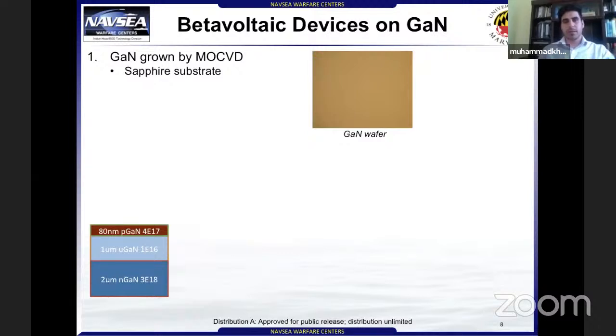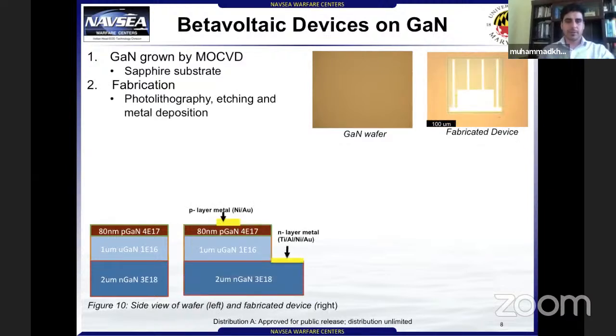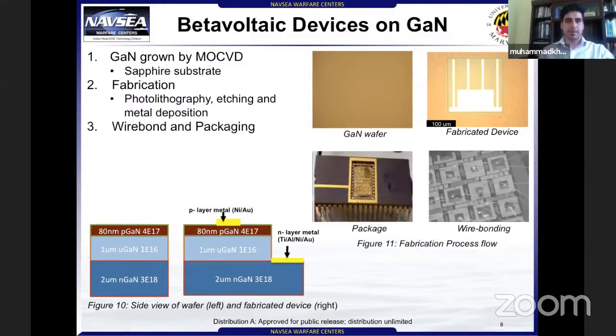We fabricated betavoltaic devices on gallium nitride semiconductor. Our GaN wafer was grown using the MOCVD method on top of a sapphire substrate. Figure 10 here shows the side view of the wafer with the doping levels and layer thicknesses. Then we fabricated our devices using standard photolithography, etching, and metal deposition. You can see here on figure 10 to the right. And then we wire bonded and packaged our device into a chip carrier. Figure 11 shows the fabrication process flow. Then we characterize our devices, which I'll talk about next.